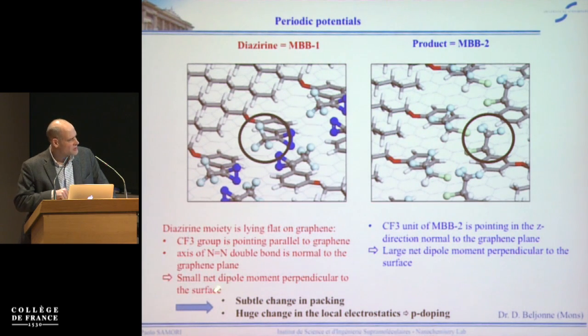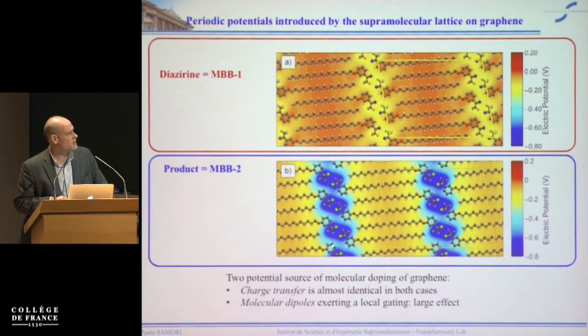And so we have a subtle change in packing, but a huge change in local electrostatics, and this generates a p-doping effect. Now, this kind of p-doping effect can be really used in order to create some one-dimensional periodic potential. A bit more modeling revealed that there is a minor role played by charge transfer, but a major role played by the molecular dipoles that are exerting a local gating effect.